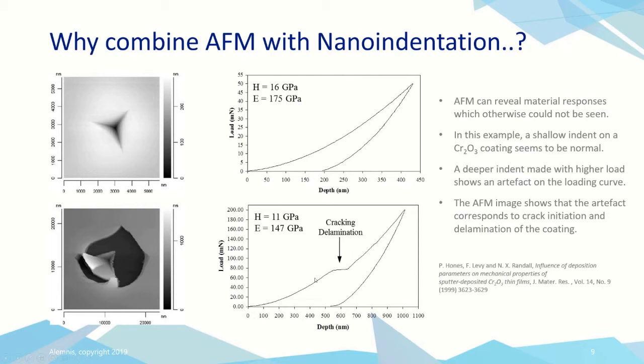we notice that there's a step on the loading curve. Now, if we don't have any imaging technique, we don't know what that's due to. It could be cracking, could be delamination, we don't know. And it's only by actually imaging the surface, as you see on the left here, that we see that we've got both cracking and the coating is completely delaminated from the substrate. So it's very important to be able to understand that.